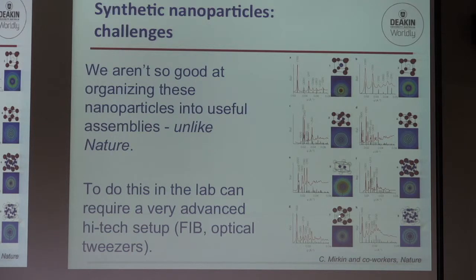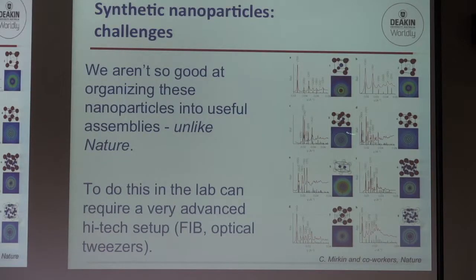They managed to accomplish this by a technique where they fuse DNA onto the nanoparticles, and they can only do this with gold. So the technology is there to conjugate a DNA molecule onto gold, and you can do that with a controlled density of the graft. And by manipulating the actual DNA strands that you have conjugated onto the gold surface, and by manipulating the conditions, you can get these different crystal structures of these superlattices.